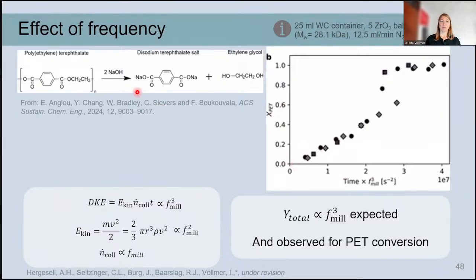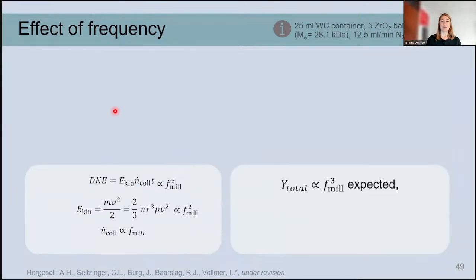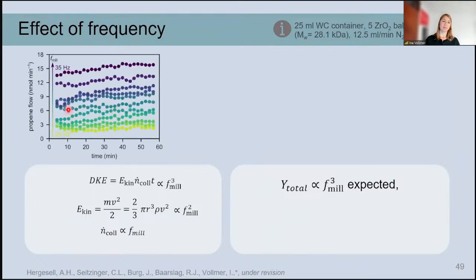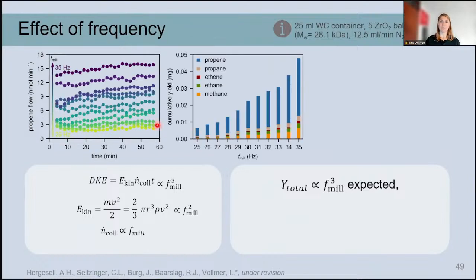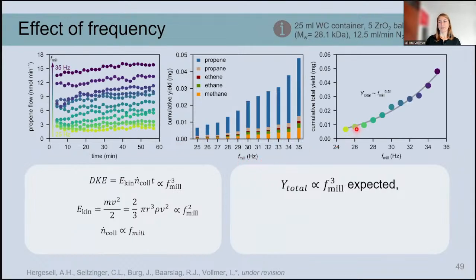However, in this process, the most important step is to mix the sodium hydroxide with the polymer, so to get this contact right. And in our case, we are looking at a little bit of a different mechanism. So we milled at different frequencies and looked at the yields of different products. And you can already see that, yeah, it could be linear, but it already does not look fully linear with the milling frequency. And then we tried to see how the yield behaves in relation to the milling frequency.